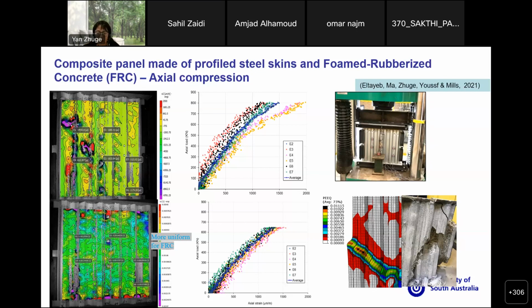Overall, the foam rubberized concrete can effectively consume recycled rubber particles from waste tires, and it is a suitable option as the filler material in profiled steel composite walls. You see the difference between the normal concrete test and the crumb rubber concrete test. It has much more uniform distribution compared to the normal concrete. This is with 20% or even more rubber content. That is a typical failure pattern of rubber concrete.